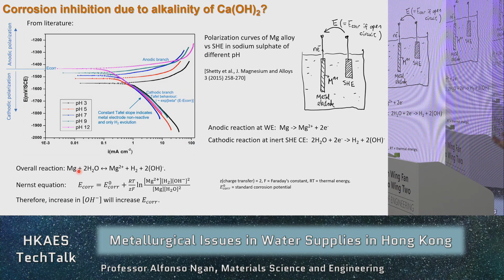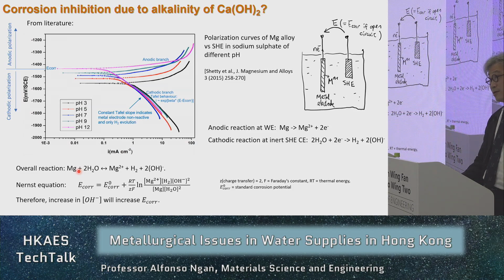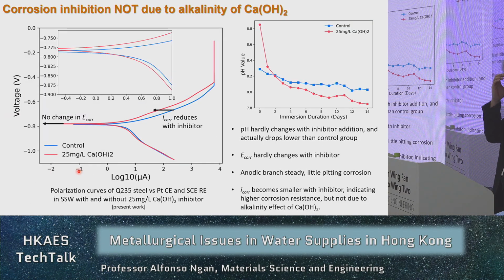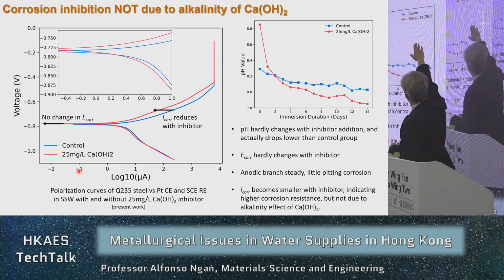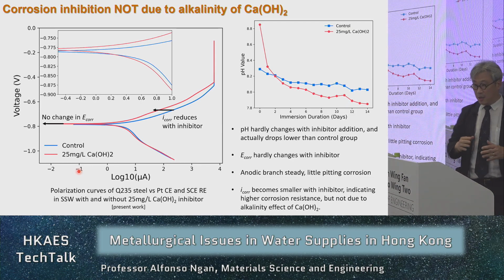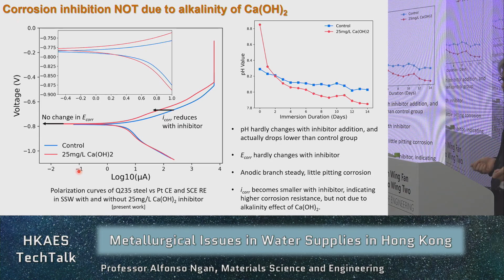That is one, in fact, the very first mechanism that our WSD colleagues thought of. Okay, so when they saw our result, they said that, oh, it's obvious because you add lime into the water, that will make the water more alkaline. That must be the mechanism. And we thought that was the reason as well, until we carried out a more detailed study. And actually, we found that for the amount of lime that we have added, which is this amount already, 25 milligrams per liter, the change in the pH value is minimal.